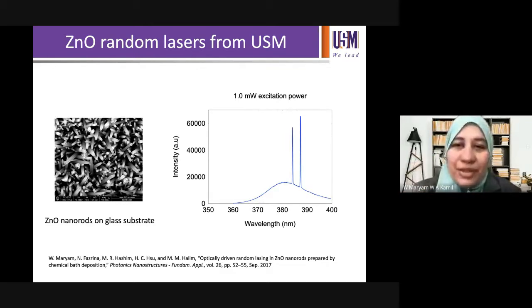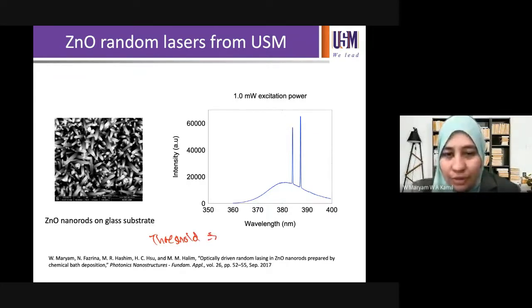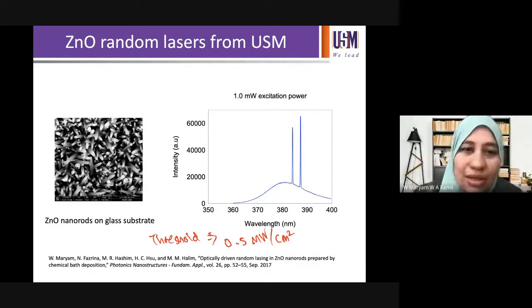So this is something that is not discussed very much in random lasers, but it answers the question. Yes, you can see random lasing in zinc oxide nanorods that are grown by a simple chemical bath deposition method on standard glass substrate. Okay, but I did not write here, the threshold for this to occur is actually at 0.5 milliwatt per cm squared. So that's quite high. Okay, so we saw that we can achieve lasing.